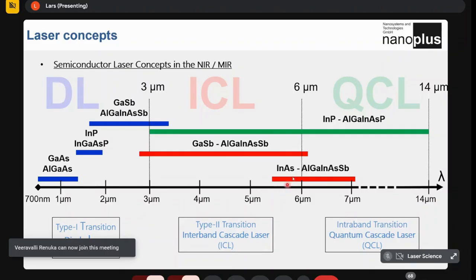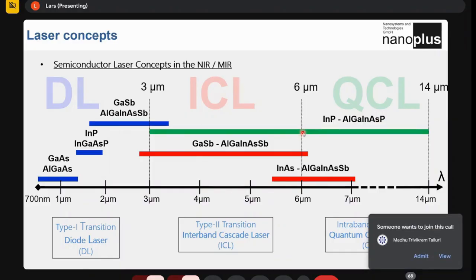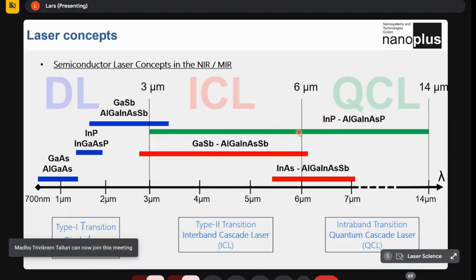And then the quantum cascade lasers, they really go down to 3 micrometers, but we only use them above 6 micrometers. I will come to that in a minute. Up to 14 micrometers. So with these 3 technologies, normal diode lasers, interband cascade lasers, or quantum cascade lasers, we can cover the whole spectrum of wavelengths between 700-something nanometers, 760, up to 14 micrometers.